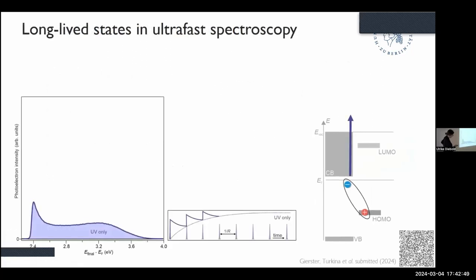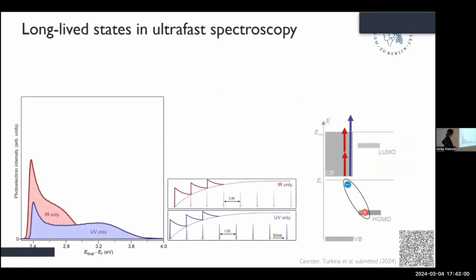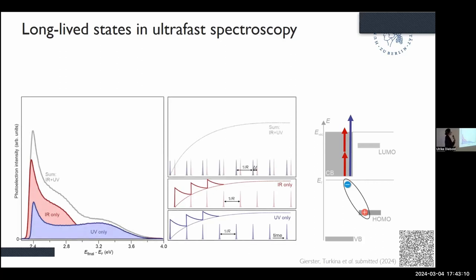So how does all this connect to the experiment? Well, we do in fact see a feature with an energy that would match the binding energy, and we see it both with UV and IR single spectra, so we can pump and probe it with all the photon energies that we use in the experiment. But this is not a proof of any correlation. This could also be the spectral signature of a simple defect state that is sitting below the Fermi energy. In order to show that this is a hybrid exciton state, we need to show that we do the excitation in the molecule, and then this generates this feature.